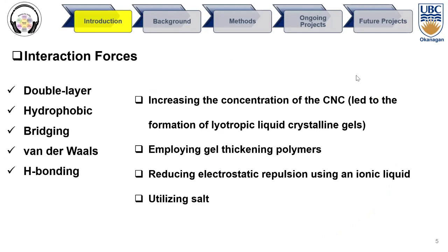We can increase the concentration of the CNC, where CNC is cellulose nanocrystals, or CNF, cellulose nanofiber. Whenever we increase the concentration, we form lyotropic liquid crystalline gels, and we can have a strong gel. Later I will explain why we are going to increase the viscosity of these types of materials and why this is so important for 3D printing, especially inkjet printing or extrusion 3D printing.